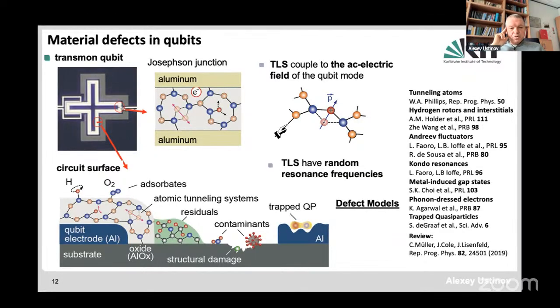So the defects occur not only in the tunnel barrier of the junction, which you see here on the top, as an example of the layer between two superconducting materials, but they can also occur on the surface of the superconducting material. Let's say due to adsorbates, they can be just atomic tunneling systems in the oxide on the surface. There can be residuals of the photoresist, some contamination. There have also been proposals that these could be defects due to trapped quasi-particles, like you have a small region of reduced gap on the surface, and a quasi-particle can come there and, not being able to pair with another electron, this excitation would stay there for a long time.